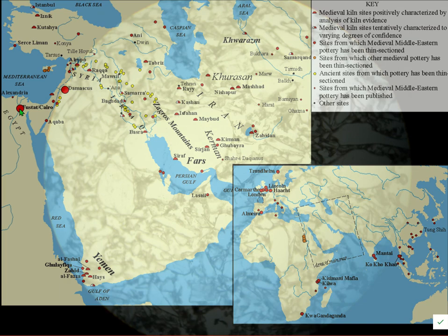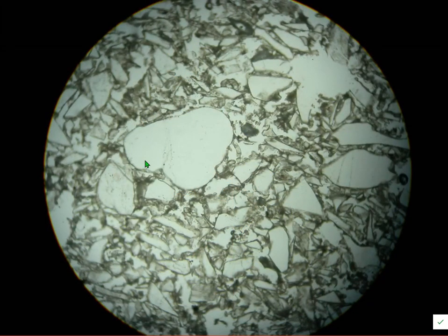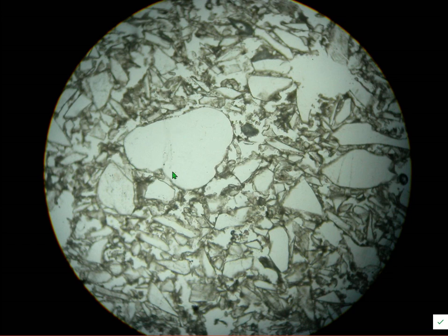Pottery fabrics for both Damascus and Fustat include sand, as in the Ayyubid and Fatimid periods, but the sand is distinct between the two sites. You can see the sand grain — even where crushed you can see traces of the curved parts. The Fustat quartz has a lot more cloudy areas called fluid inclusions, while Damascus quartz has very few. The sand grains in Fustat fabric also tend to be statistically larger, so it is possible to distinguish between the two.